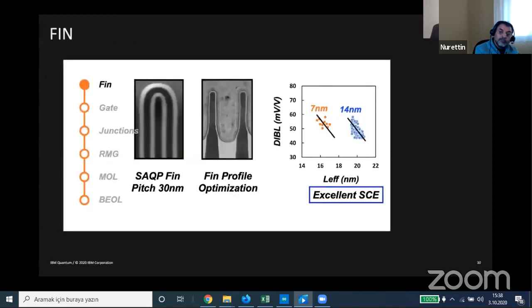Shown here is the fin enhancements. Here we optimized the fin profile. We used self-aligned quadruple patterning as described earlier to achieve a very nice fin pitch of 30 nanometers. Shown here is the DIBL, which is a measure of short channel effects as a function of gate length. So we can achieve for the 7 nanometer node almost roughly 5 nanometer shorter gate length for the same DIBL.